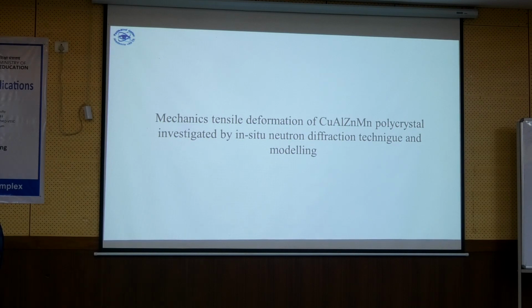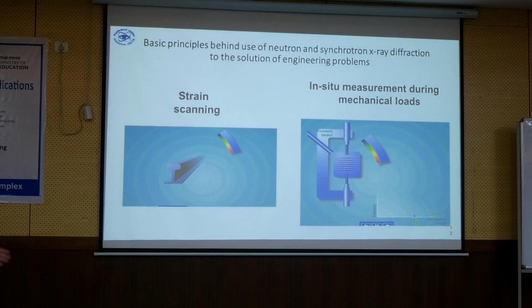Okay, and well, now because I wanted to make this talk consistent, I will continue with experiments on copper, aluminum, zinc, manganese polycrystal, which we did later on, about after 2000, with in situ neutron diffraction technique and modeling. So please forgive me that I am now jumping into this neutron diffraction, but this is because I would like to complete the talk about the copper-based alloys. And so why in situ diffraction studies? Because if we have the polycrystal and we are looking at processes which derive from phase transformation, the diffraction is the wonderful tool.